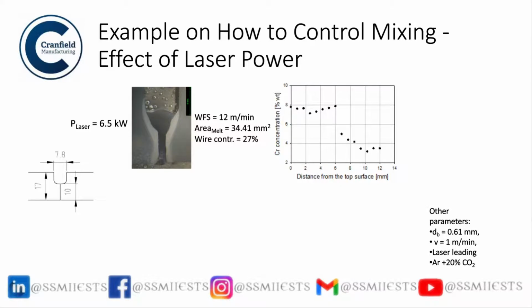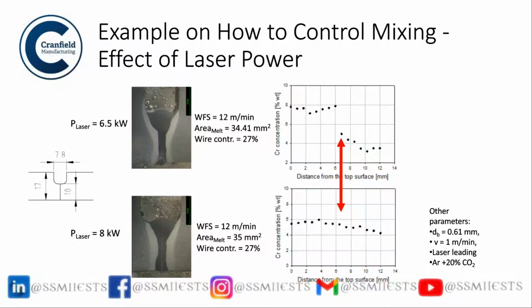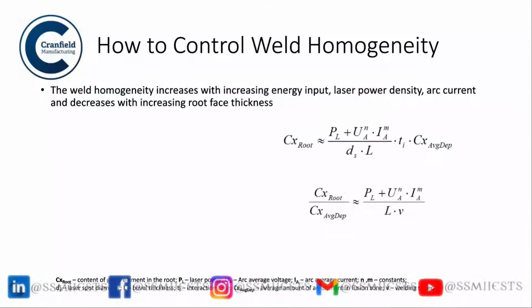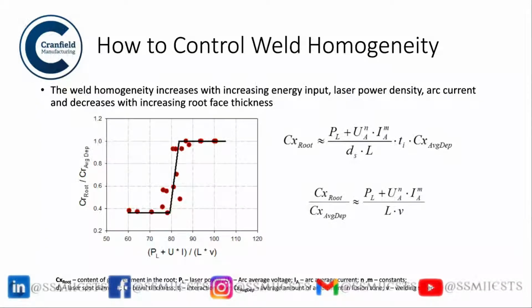And as you can see here, with the same wire feed speed, if you increase the laser power from 6.5 to 8, you can practically minimize. So what is happening in these two situations is more filler, more dilution happening with the parent, and as a result, a better weld is forming with the proper mixing of the filler with the parent. So then we try to derive this equation basically based on the understanding.